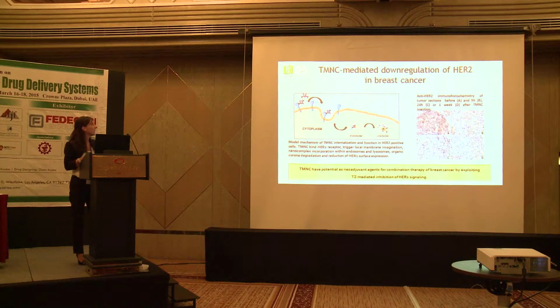in which the nanoparticles, once bound to HER2 receptors, were rapidly internalized via receptor-mediated endocytosis and degraded inside the cells, with the disintegration of the fluorescent-labeled organic component. This mechanism would explain the drop in fluorescence that we have seen in the previous slide, although the metallic core of the nanoparticle can still be present inside the cell.